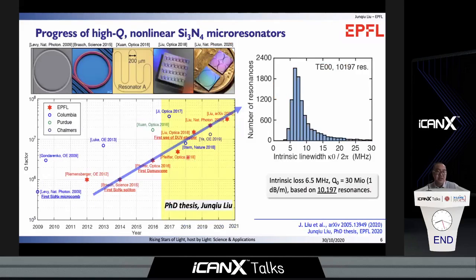This chart shows our silicon nitride microresonator Q improvement, or loss reduction, with our progressive fabrication process, together with results from other groups. Since the first low-loss silicon nitride photonic integrated circuit demonstrated in Professor Michal Lipson's group, with the continuous effort from the entire silicon nitride community, today people are routinely able to achieve more than 10 million Q factor of the microresonator. To estimate the loss of our silicon nitride microresonators, we measured the linewidth of more than 10,000 resonances and analyzed their statistical distribution. As shown here, we have achieved an intrinsic loss of 6.5 megahertz, and this corresponds to a Q factor of 30 million and a linear propagation loss of 1 dB per meter.